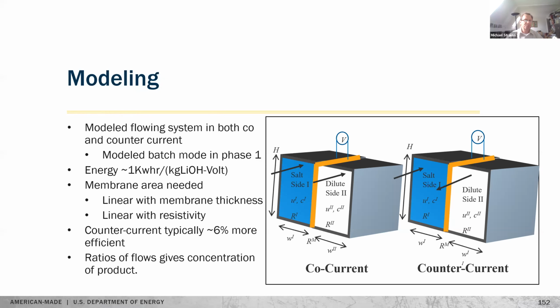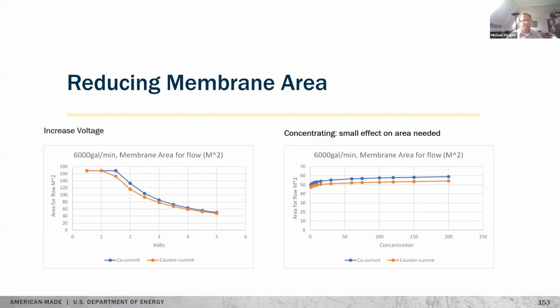Next slide, please. So here are some results. The graph on the left shows the membrane needed for a 6,000 gallon per minute brine system. The blue lines are for co-current flow, the orange lines for counter current flow. At 1 volt, you need about 170 square meters. Going to 5 volts reduces the area to about 50 square meters. So we think that's why we chose the 5 volts.